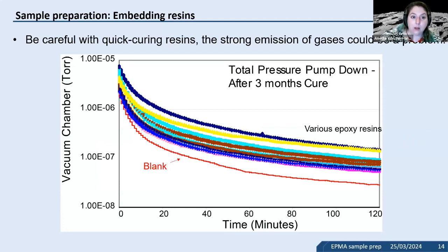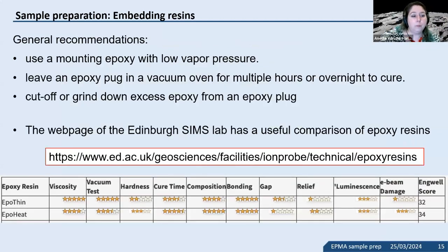And so usually I'm a fan of slow curing resins and letting them sufficiently cure and not just rush my whole prep, because that really helps then with a pump down before we can do analysis and overall quality of the data. So there's some general recommendations. Again, use a slow curing epoxy. It can really help to leave it in a vacuum oven for hours or overnight to cure and outgas.